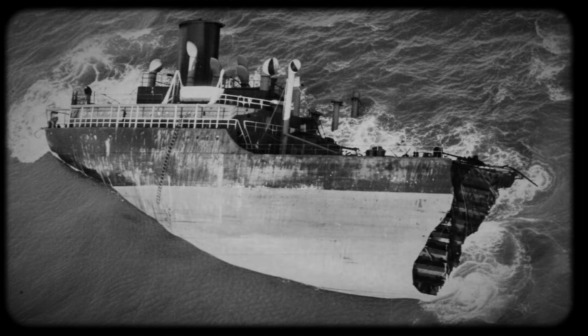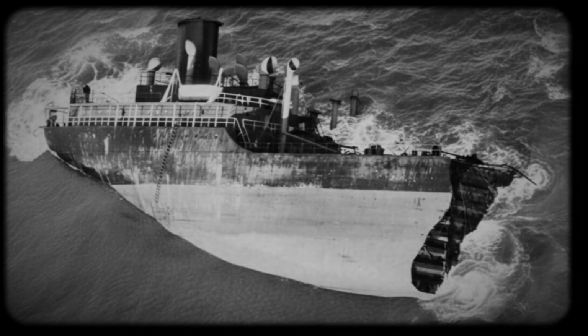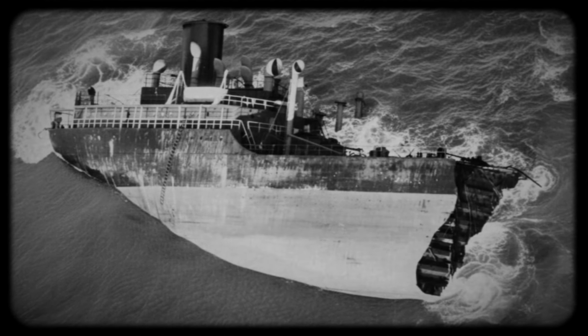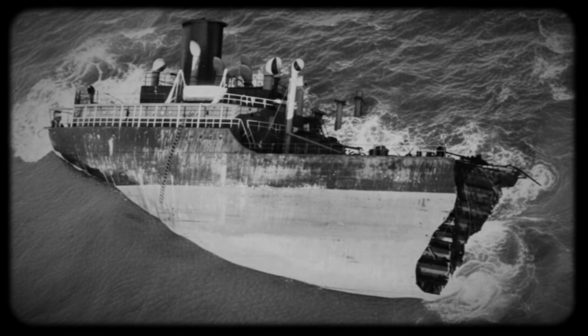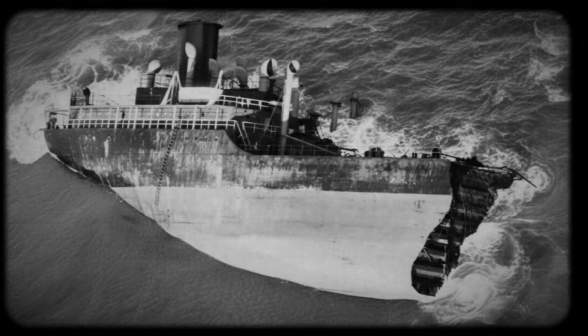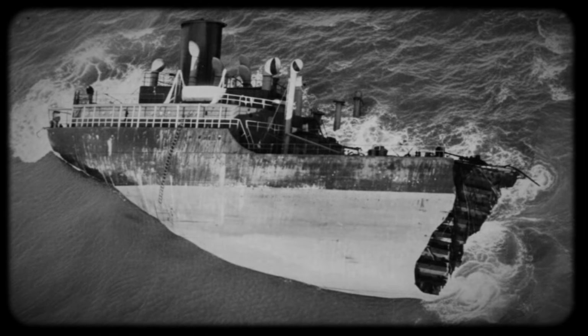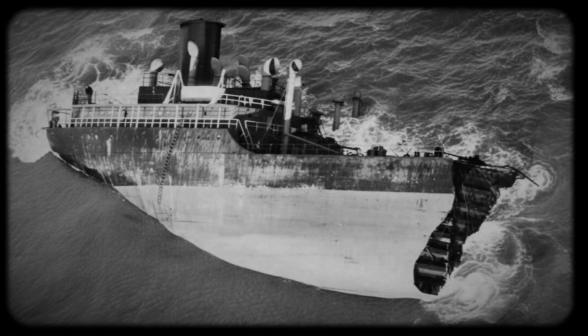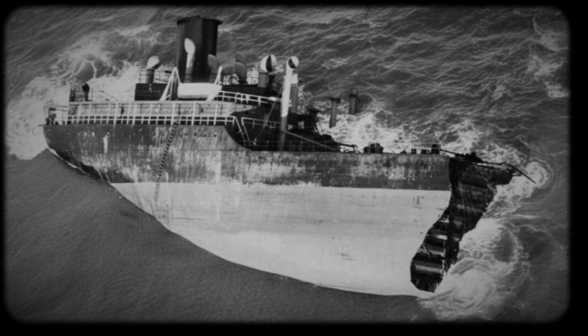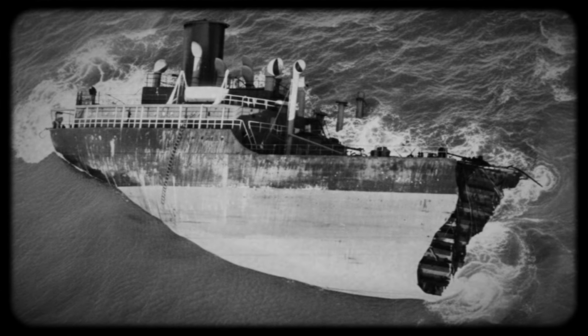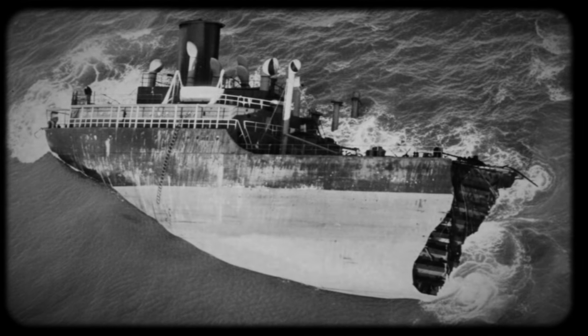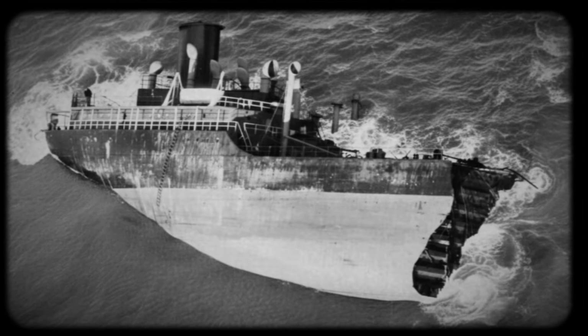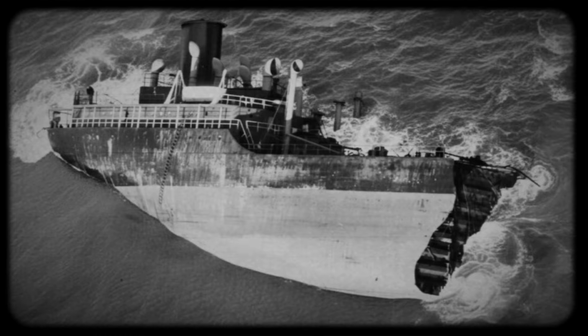A crack initiates at a stress concentration point, say a square hatch corner. In ductile steel, that crack would grow slowly, requiring tremendous energy to propagate. But in brittle steel, preloaded with residual stress, the crack races through the material at hundreds of feet per second. The stored energy in the residual stresses drives the crack forward. In seconds, it can split an entire ship. Tipper compiled these findings into a report that would revolutionize both shipbuilding and metallurgy. But the report's key recommendation came directly from Bessie Hamill's observations. Change the welding sequence.